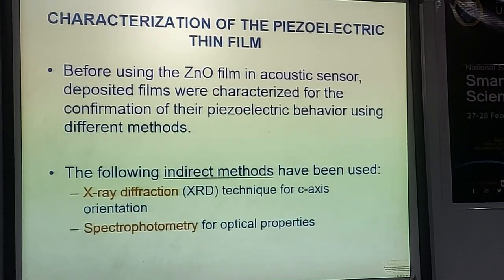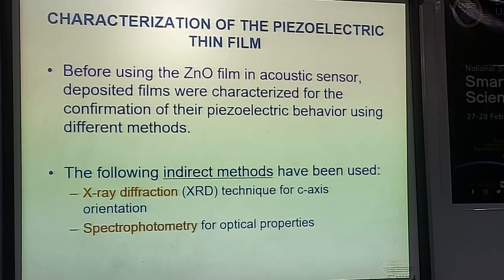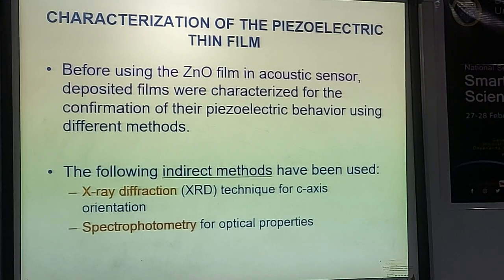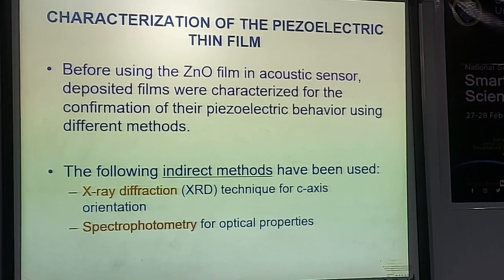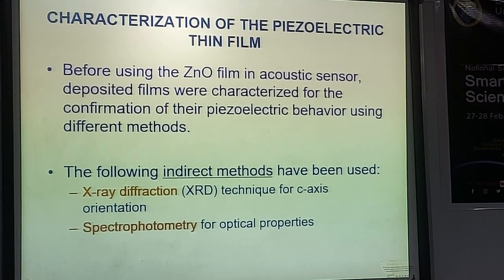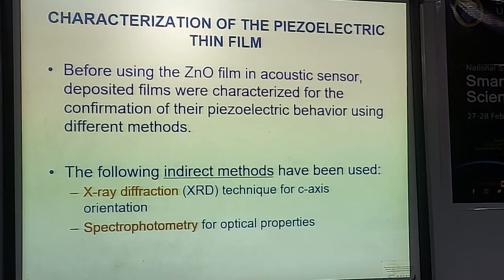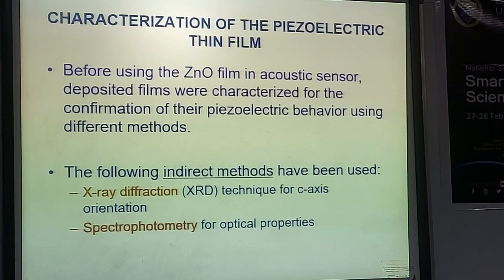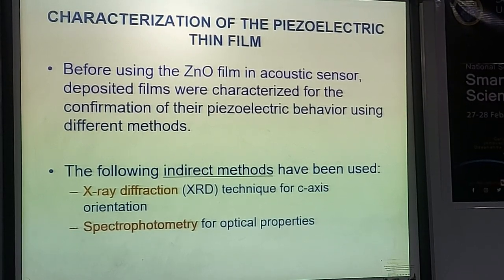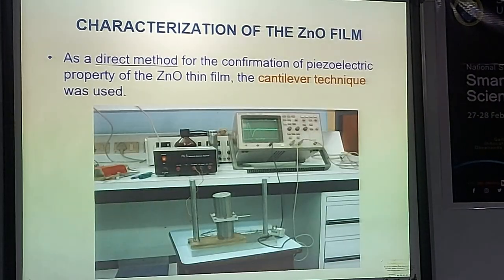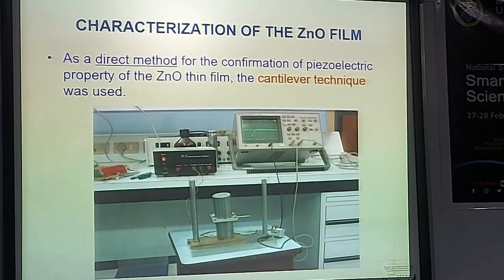And again, after the preparation of the zinc oxide film, in order to make sure that it is piezoelectric in nature, we characterized it by some indirect methods like X-ray diffraction, photometry method, etc., which give an idea whether the deposited film is piezoelectric or not. These are the indirect methods. There is also a direct method called the cantilever technique.